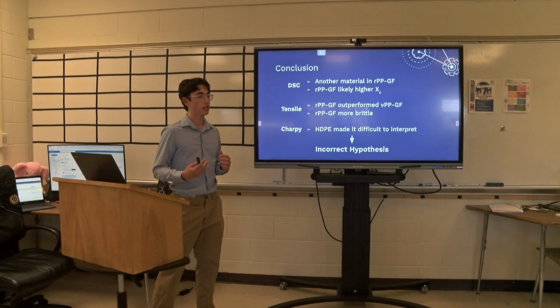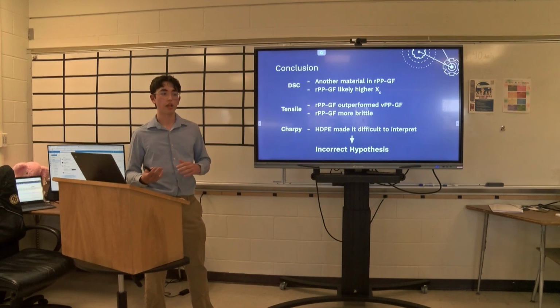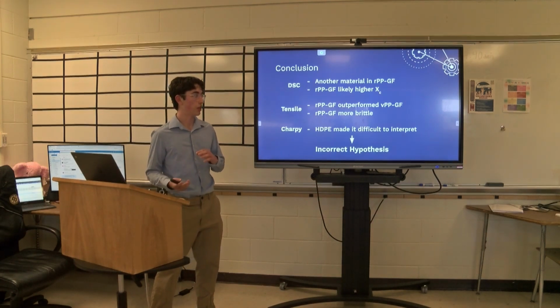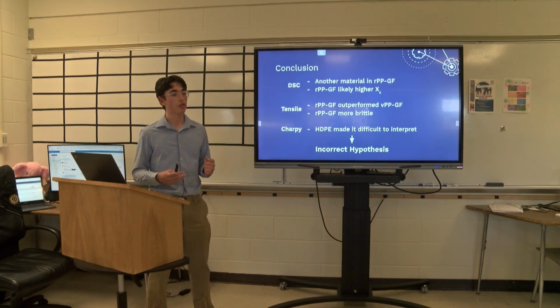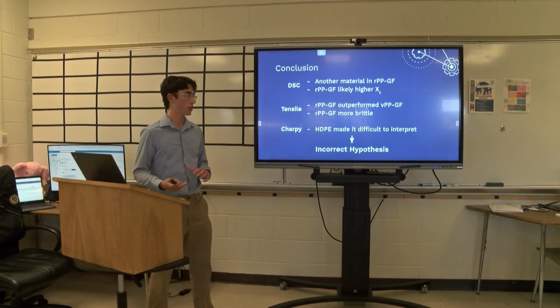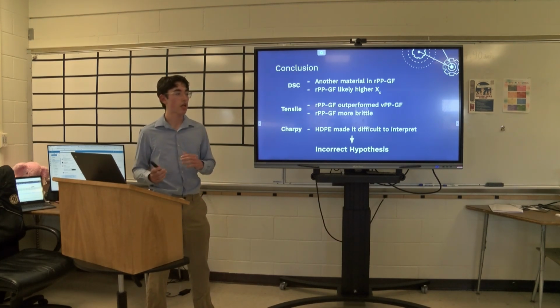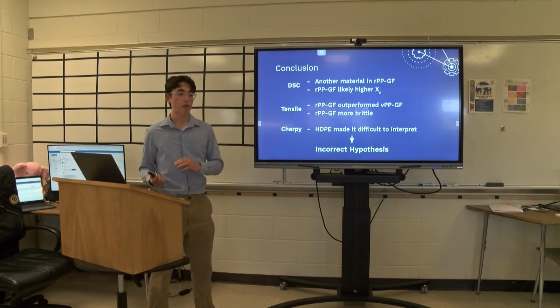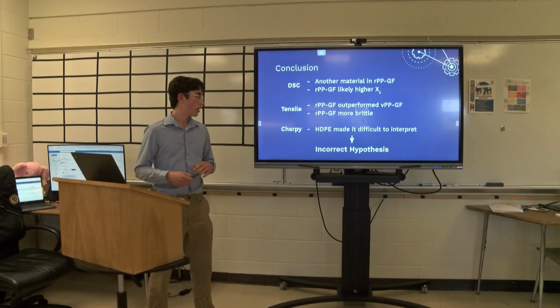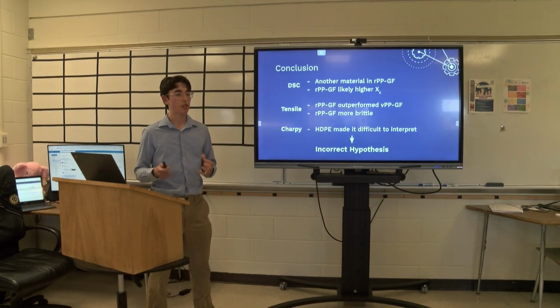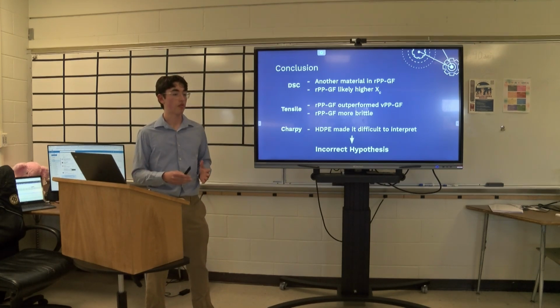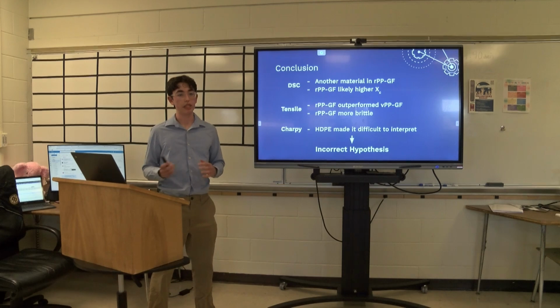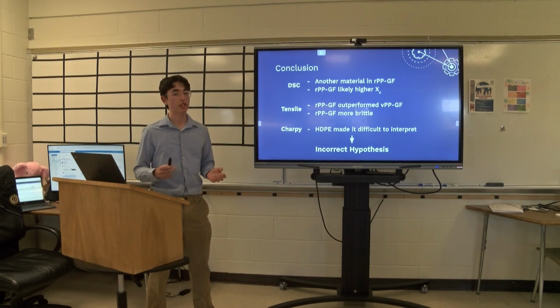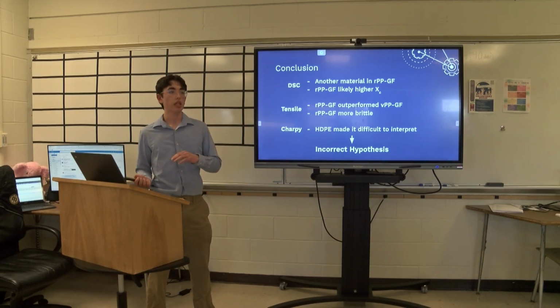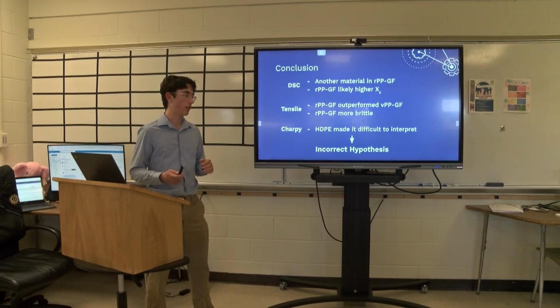So from the DSC test, we know that there's likely another material present within the RPPGF composite, and also the recycled material likely has a close to, if not higher, percent crystallinity. From the tensile test, we know that the recycled material often outperformed the virgin material in terms of strength, but was more brittle. From the Charpy test, no major conclusions were made on glass fiber reinforced polypropylene because the addition of HDPE made it challenging to know what the impact strength would have been without the addition of HDPE.